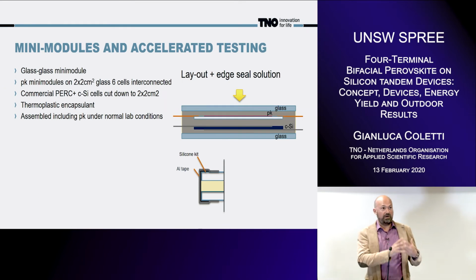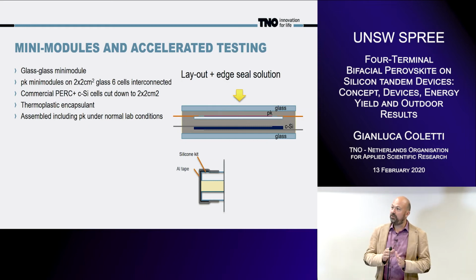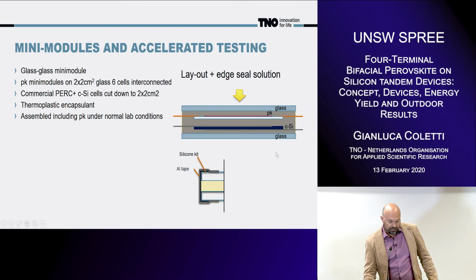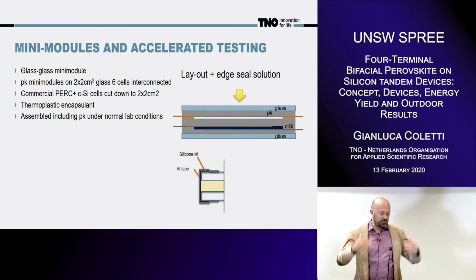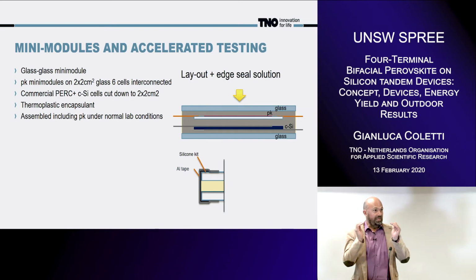These were the result of our calculation. Then we need to make minimodules. For doing that, we use perovskite with 6 interconnected cells, 2 by 2 square centimeter. We use the same PERC cell, but we cut it down to the same size as the top device. We encapsulate with glass minimodule. We use a thermoplastic encapsulant, and the assembly is done in normal lab condition, also for the perovskite. We paid special attention to the edges, because that's where moisture can penetrate. So we use silicone kit and aluminum tape to really protect the edges.